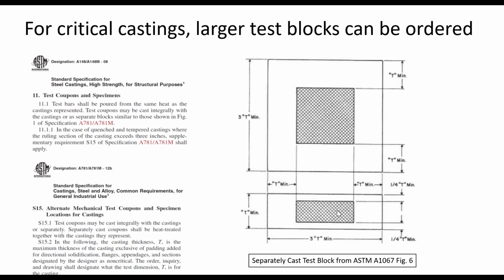The center is the last place to solidify typically, and so it has segregation and microporosity, and you don't load it normally because you have some bending moment, and so it's not particularly useful to know the properties in the center. The surface is going to have properties that look like the keel block because it cooled fast. And so T/4 is determined to be the most practical way of characterizing the properties of the casting with that section thickness. And so that's why we do a T/4 test. And we do it in a 3T by 3T by T section.